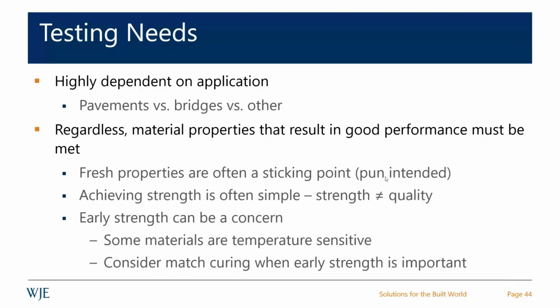One thing I will say for structural applications that we're finding very useful and we're becoming major advocates of is match curing. This is getting away from setting your cylinders on the slab or on the side of the road or even in a box, but instead, you have a specially designed box that monitors the temperature of the concrete in situ. It duplicates that temperature within the box. So, in other words, the concrete is cured at exactly the same temperature as it's experiencing in the field. And so, if you're looking at time critical structural elements that you need a certain strength to tilt, match curing is a wonderful way to go.